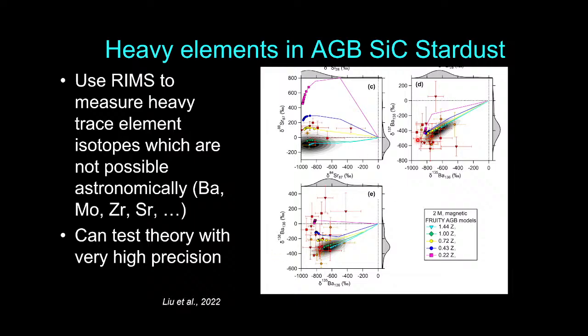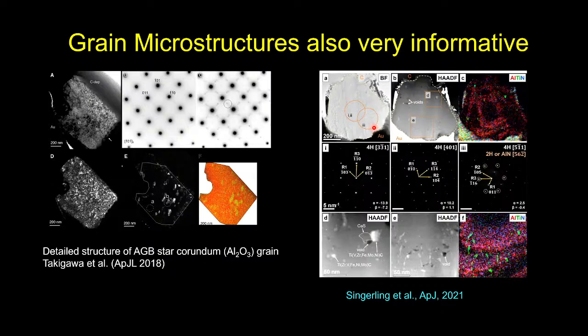And I showed that comparison of oxygen and carbon isotopes to astronomical observations, because those elements can be measured spectroscopically. But we will never have the technology to measure the strontium isotope composition of an AGB star through a telescope. The strontium's just too low in abundance, and the shifts in spectral lines are too small to be discerned. So this is the only way to get at this data. So it's a unique way of studying stars. We also can look at the grain structures, what they're made out of.